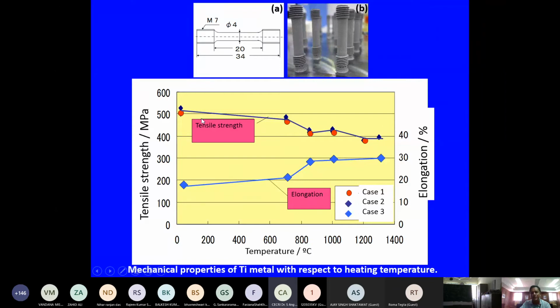Here you can see an example where the as-printed sample has 500 to 530 megapascal, and if you increase the heat treatment temperature, the property goes down to 400 MPa. But 400 megapascal is more than enough, because for bone application, a maximum of 100 megapascal is more than enough. Since 400 is well beyond the strength range needed, we can say that even if I heat the sample at 1200 or 1300 to avoid loose particle release, which could make it cancerous or something, although the strength may go down by 100 MPa, it is well above the mechanical strength required for bone application.